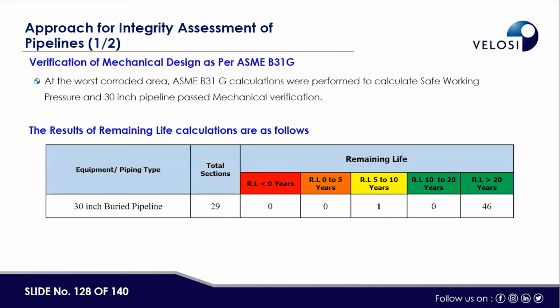Then verification of mechanical design as per B31G at the worst corroded area. ASME B31G calculations were performed to calculate the safe working pressure, and the 30-inch pipeline passed mechanical verification. You can see as per this line, for example, RL 5 to 10 is 1, and RL greater than 20 is 46. Basically, components were there in the pipe. This is the one weakest component.